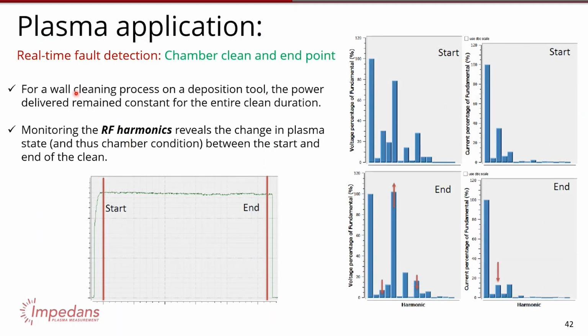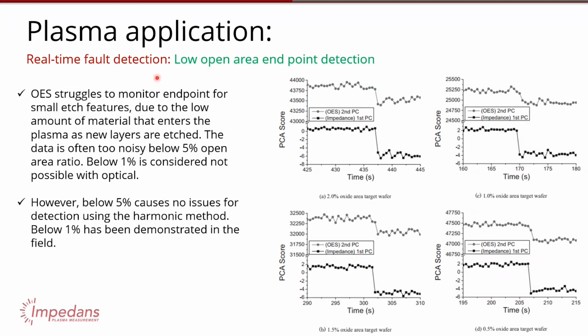I'll very quickly say you can do chamber clean and endpoint detection. Even if power stays the same over the process, if you look at the harmonics at the start and at the end, you get totally big changes in the harmonic spectrum because the cleaning happened. There are also publications looking at low area endpoint detection. That's a challenge of the industry, monitoring below 5% or below 1% of the wafer being etched. Optically, that's really difficult now.